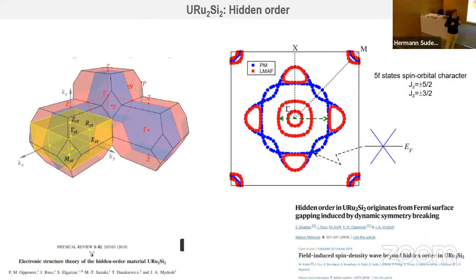But electronically, there is a gap which opens, and which makes the Fermi surface nearly kind of split into two parts, but it does not lead to a structural transition. So this can be reproduced by theory, by taking into account the spin states and how degenerate they are at the normal phase at high temperatures and in the ordered phase at low temperatures. So this tells you that, of course, the F levels have some role in this phenomenon. And you go from the usual Brillouin zone of the tetragonal structure to another one, which is the simple tetragonal Brillouin zone. So this is something which we know.